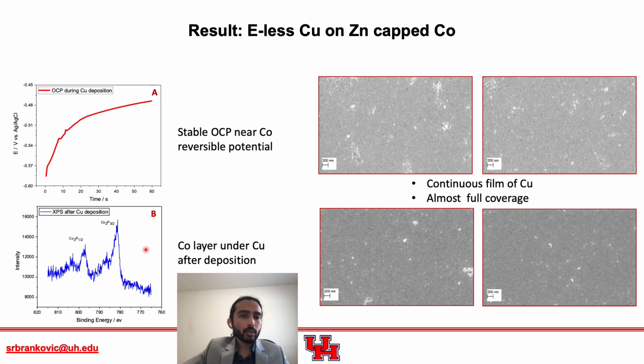And graph B shows XPS results where we can see cobalt peak as well. These four images on the right side show SEM of the substrate after copper deposition, and we can notice that there is a continuous film of copper with almost full coverage throughout the sample.